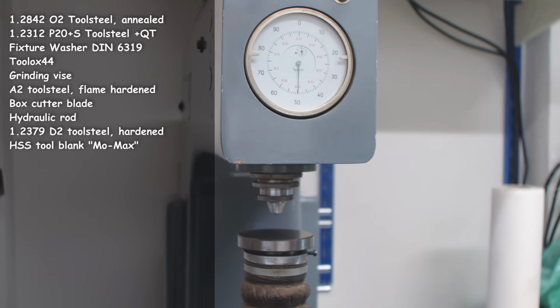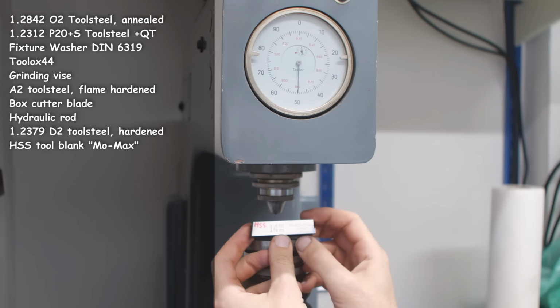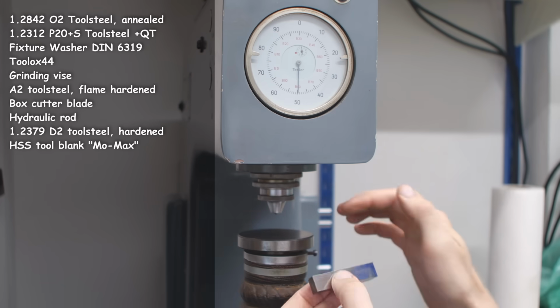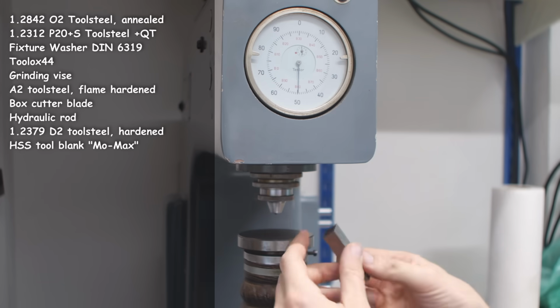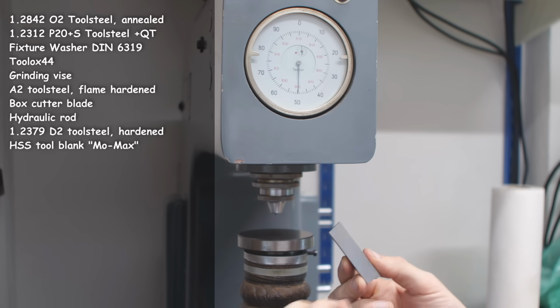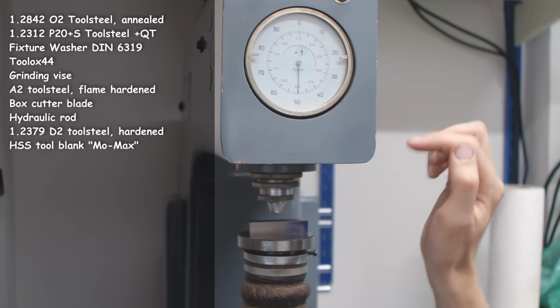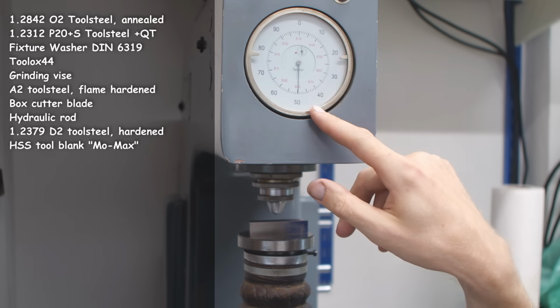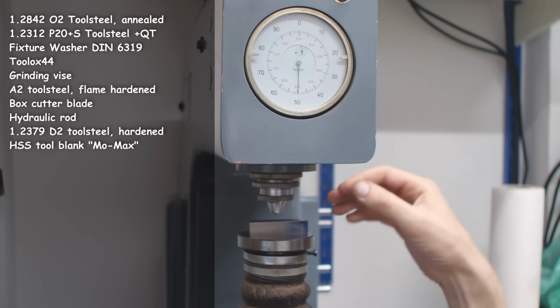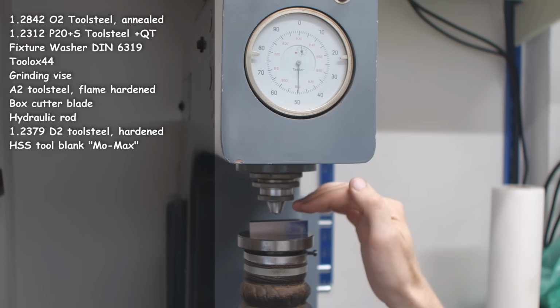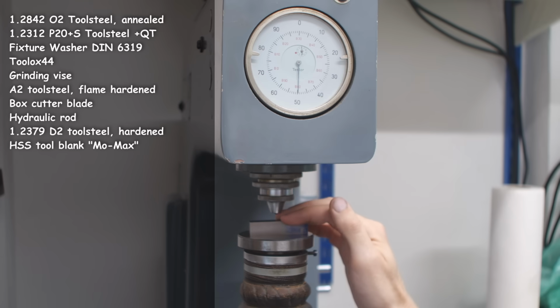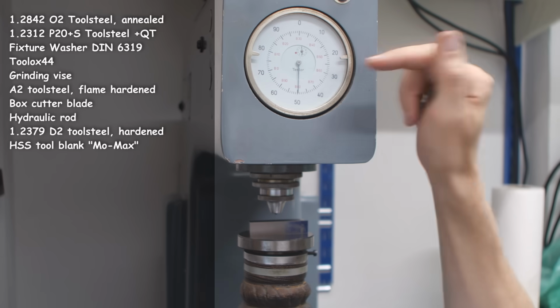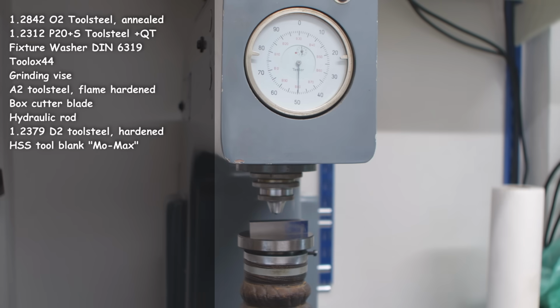Let's start with the probably hardest, with the high-speed steel. This is just a Momax Cobalt high-speed steel blank. In hardness testing, the cleanliness of the anvil surface and the cleanliness of the backside of the part are very, very important, because the hardness shown up here is a direct function of how deep the diamond can indent the material. 2 microns of depth change of the diamond is 1 point of hardness up here. So there is a direct correlation between those two things.